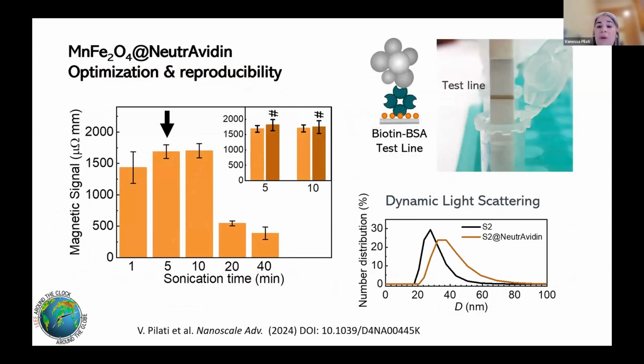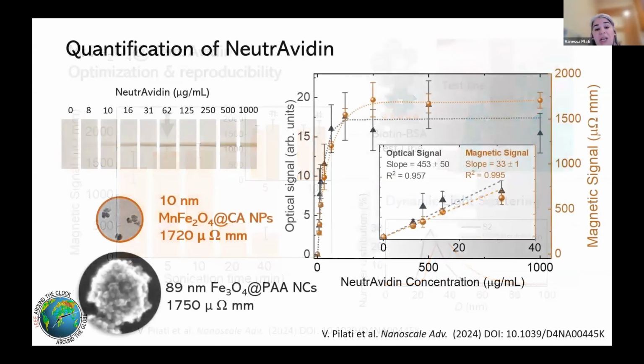We optimized the protocol, investigated the reproducibility of the bioconjugation, and we confirmed the attachment of the neutravidin molecules by using dynamic light scattering. We investigated different concentrations of neutravidin, and we saw that increasing the concentration, we are increasing the magnetic signal because we are increasing the amount of magnetic nanoparticles in the test line. So the maximum signal we achieved with these small 10 nanometers manganese ferrite nanoparticles was comparable to the huge magnetite nanocluster, which is very good.